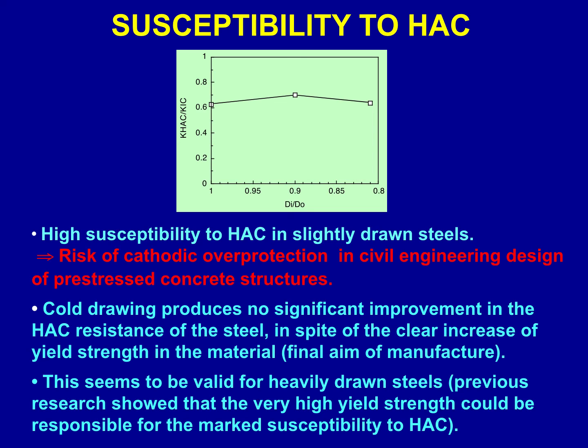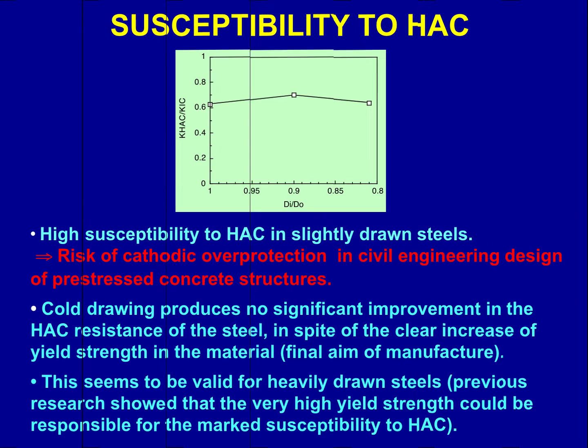Cold drawing produced no significant improvement in the hydrogen-assisted cracking resistance of the steel in spite of the clear increase of yield strength in the material, final aim of manufacture. This seems to be valid for heavily drawn steels. Previous research showed that the very high yield strength could be responsible for the marked susceptibility to hydrogen-assisted cracking.